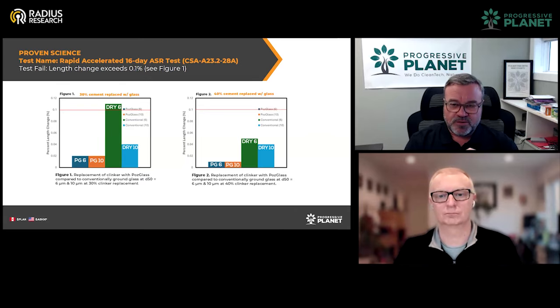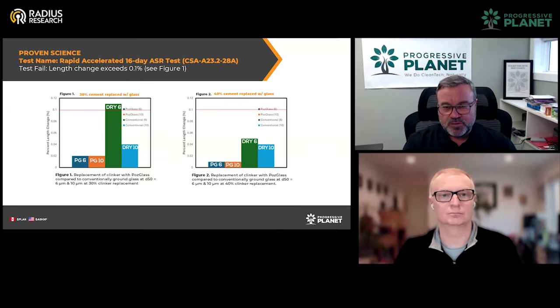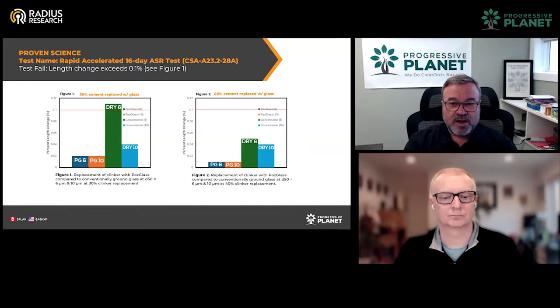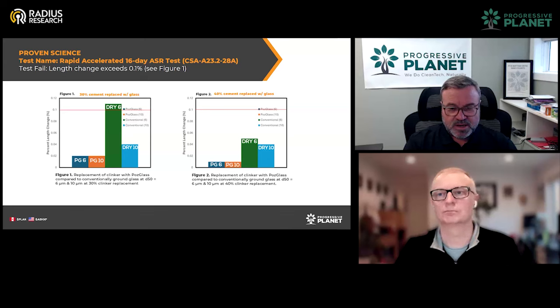Now, if you look at the first chart, in figure 1, we replaced 30% of the Portland with both PozGlass, which we call PG6 and PG10, and dry ground glass pozzolan, which we call dry 6 and dry 10. The 6 and the 10 represent the average particle size. So with the PG6, 50% of the particles are 6 microns or less, and with the PG10, 50% of the particles are 10 microns or less. Same thing with the dry.